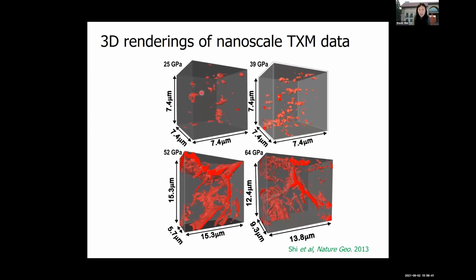in bridgmanite synthesized at 25 GPa, 39 GPa, 52 GPa, and 64 GPa. The red portions are iron alloy, and the gray portions show the surrounding silicate matrix. I think the first thing to notice is that there's a dramatic change in the iron distribution from isolated pockets to interconnected networks. This demonstrates that iron may be able to form an interconnected network between bridgmanite grain boundaries around 40 to 50 GPa.